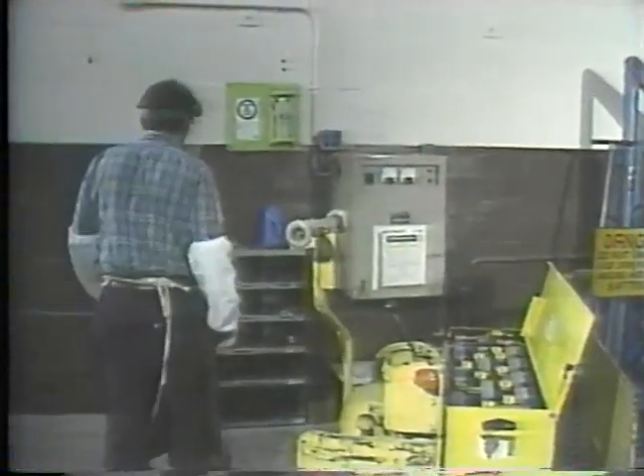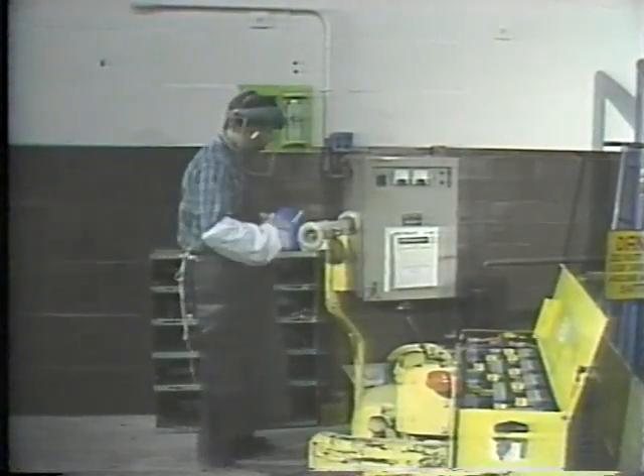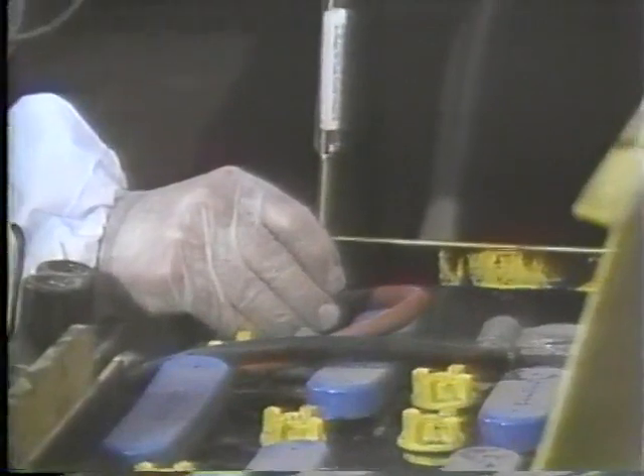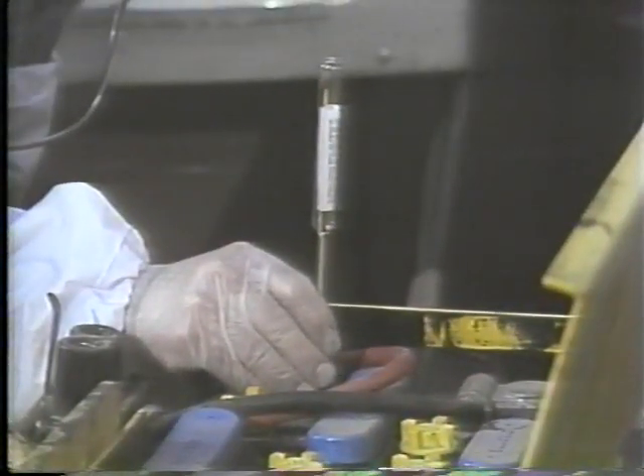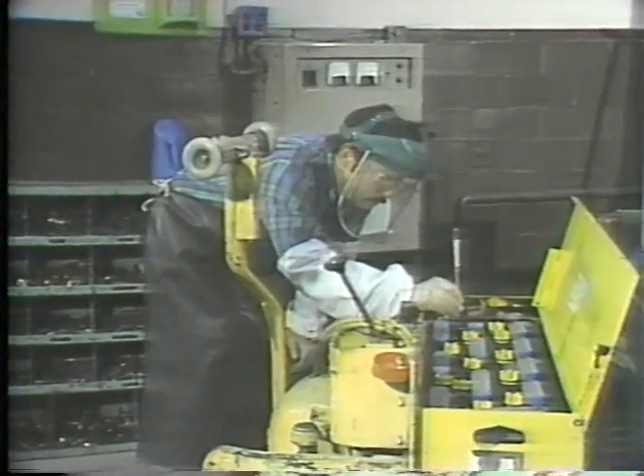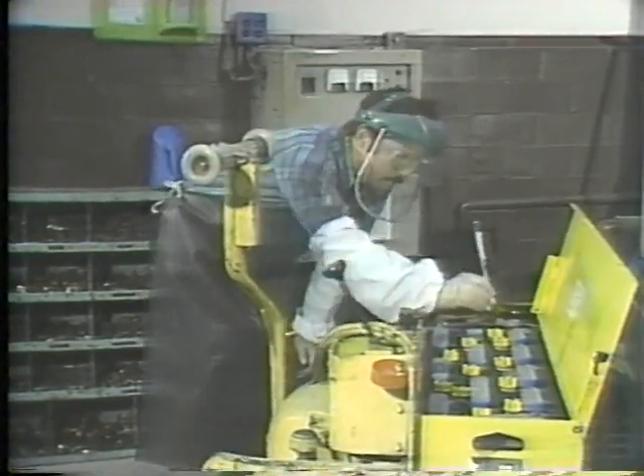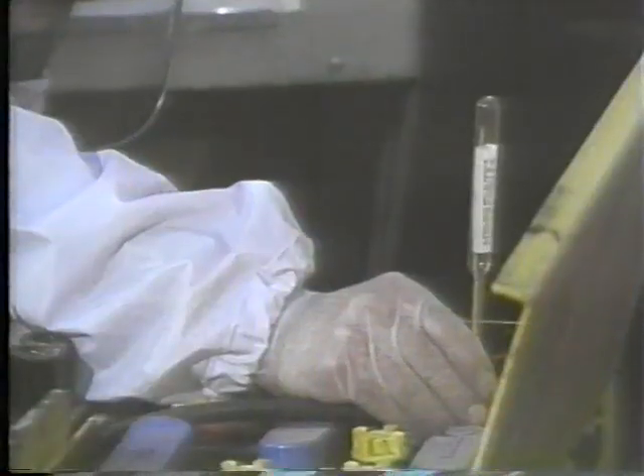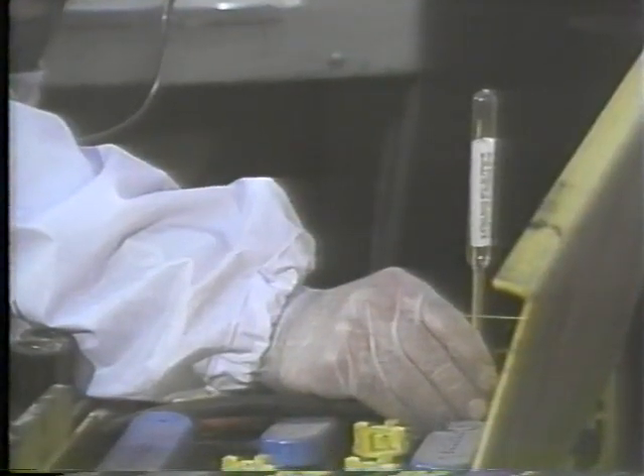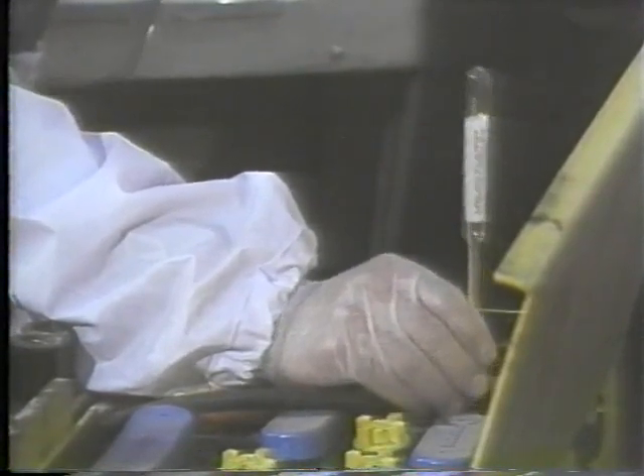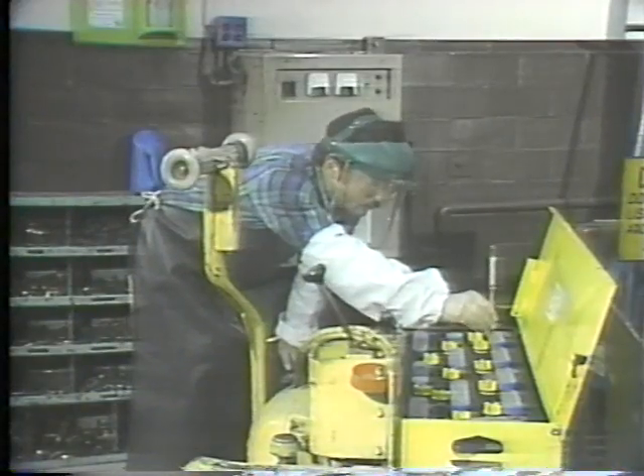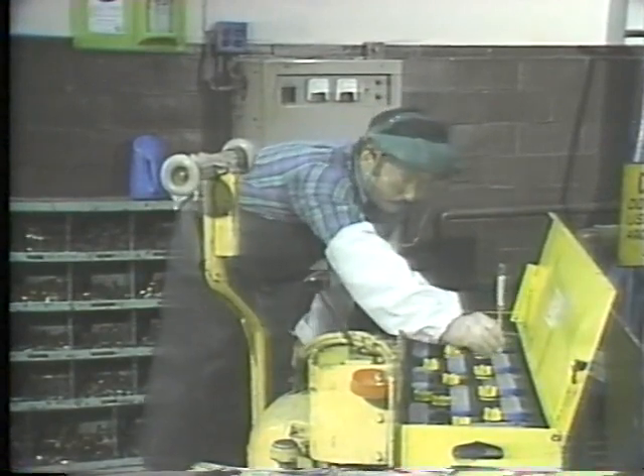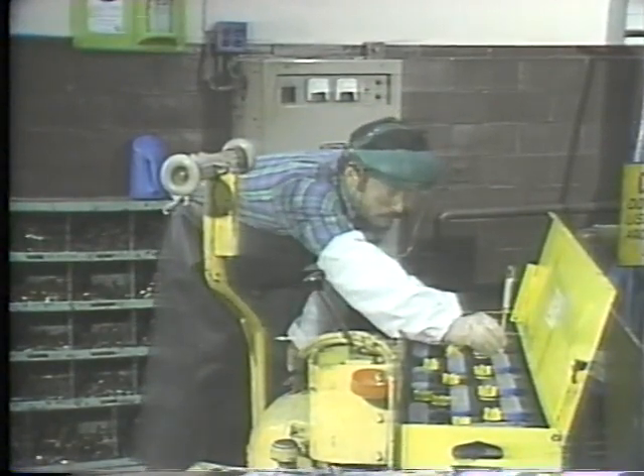A high charging rate also affects cell temperature. Although the maximum allowable temperature varies according to different manufacturers and types of batteries, 95 to 100 degrees Fahrenheit, or 38 Celsius, is about as hot as you want to go. If temperatures get much higher, you have to reduce the charging rate to prevent warping and expansion of the plates from excessive heat.